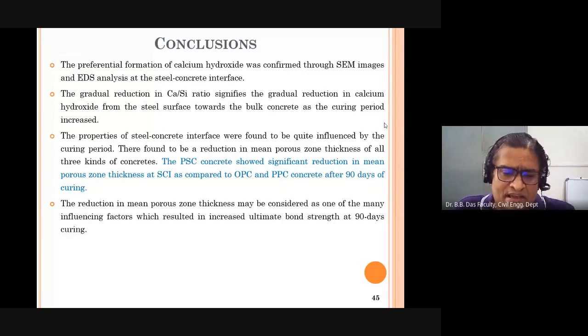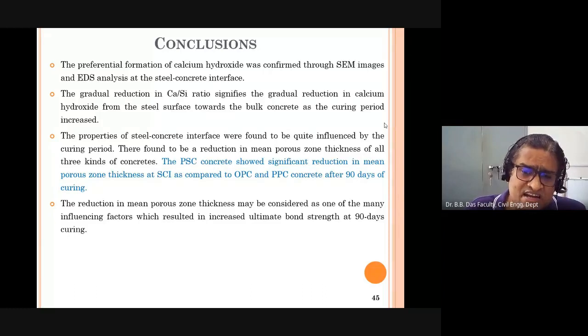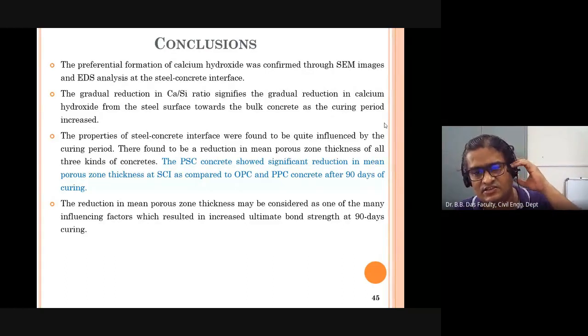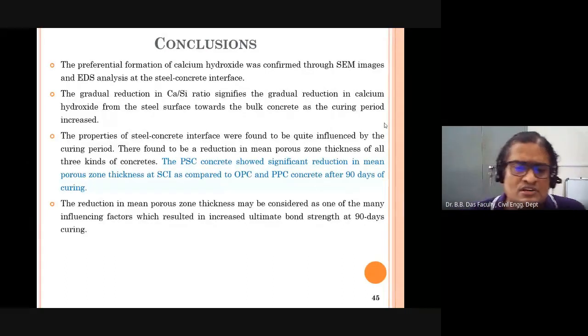The reduction in mean porous zone thickness may be considered as one of the many influencing factors which resulted in increased ultimate bond strength. I just showed you the picture. So my ultimate bond strength is increasing, and that is natural. The porous zone thickness is going to be reduced.